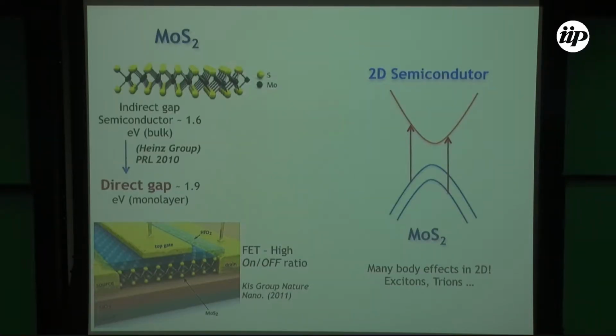For the case of MoS2, for example, there is a lot of interest in the optical properties of this material, mainly because it's a real 2D semiconductor. Before this, people used to study quantum well semiconductors and all this kind of heterostructures on III-V semiconductors, for example. And now that we have a real 2D semiconductor, we have a very large exciton binding energy. You can have trions, you can have biexcitons, even at room temperature. That allows us to study this kind of many-body effects in more detail.